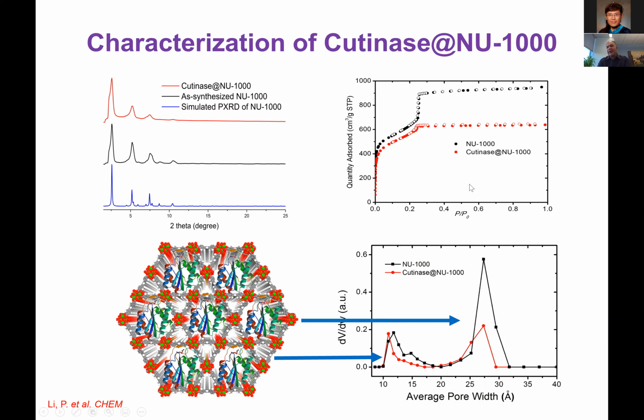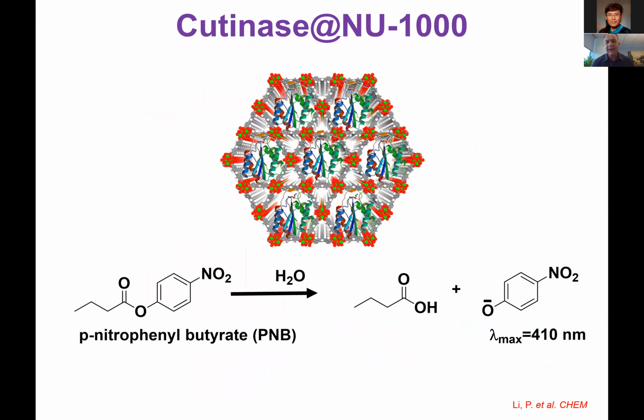Now when we put the enzyme, you could see the reduction only happens from that large channel, but not the small channel. The small channel stays the same, the pore volume did not change, and only the pore volume reduction came from the large channel. So that's indirect evidence that we really have it in the hexagons, not the triangle. And by the way, it's not surprising. It should not fit in the triangle anyways.